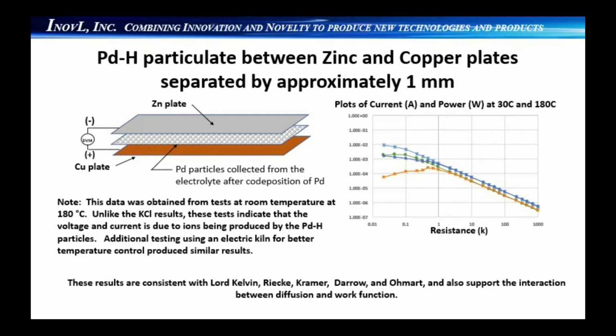The cell was taken to a lab and placed in a kiln to conduct a more controlled temperature test. Those results are still being analyzed, but while the cell voltage as a function of temperature was not as high as the initial test in my barbecue, a substantial voltage continued to be produced at temperatures above 100 degrees C. Recognizing these tests were conducted in air, we suspect the small decrease in voltage at temperature could be related to more hydrogen diffusing out of the palladium particles than that which would diffuse in. Additional tests are planned in a hydrogen gas environment.